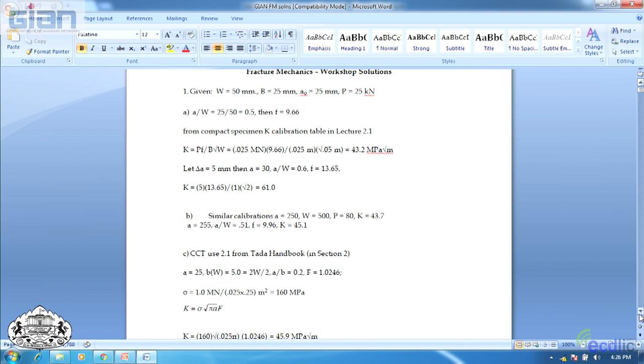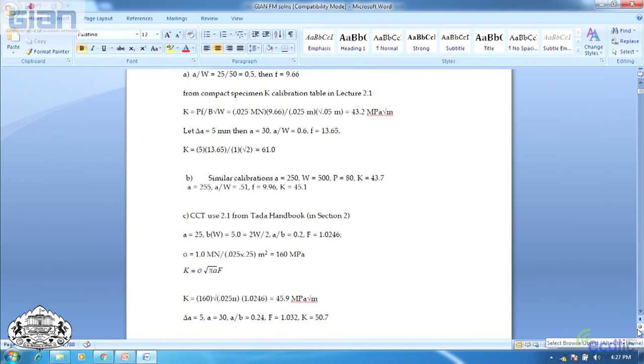So now stress, I calculate it before the crack is there as the load, 1 meganewton divided by 0.025 thickness times 0.25 meter square to get stress of 160. Using this K solution, K is sigma, 160, times the square root of pi a. This is all under the radical. I didn't have software to do that, and this is outside the radical. But anyway, 45.9.